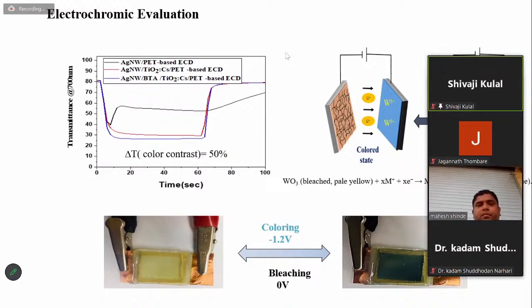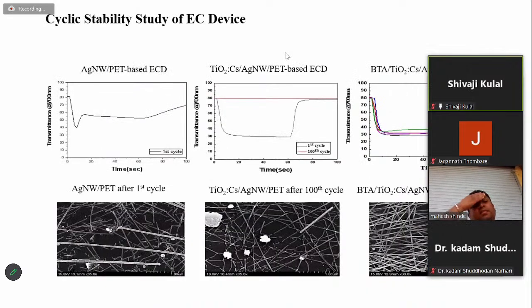After that, I studied the cyclic stability. As we know, silver nanowire is not stable in the electrochromic reaction; in the first cycle the device is damaged. You can see that this is the TCE after one cycle: the silver nanowire is completely broken, due to oxidation of the silver nanowire. In the case of TiO2 CS, the TiO2 added silver nanowire is also good for the first cycle, but after the 100th cycle the silver nanowire is also damaged.